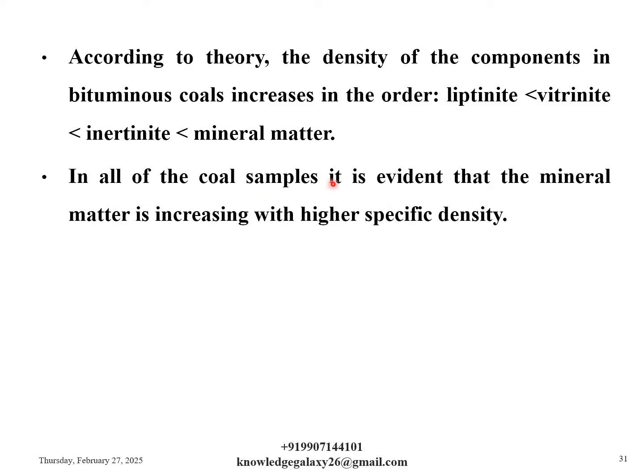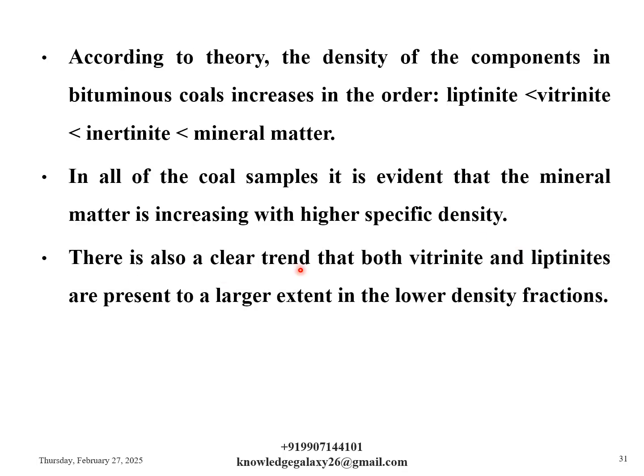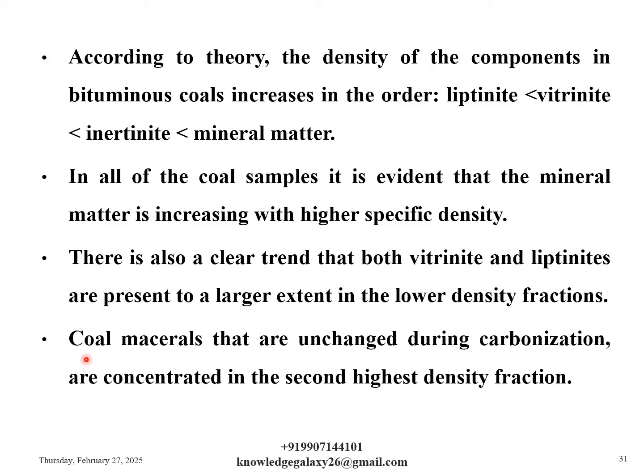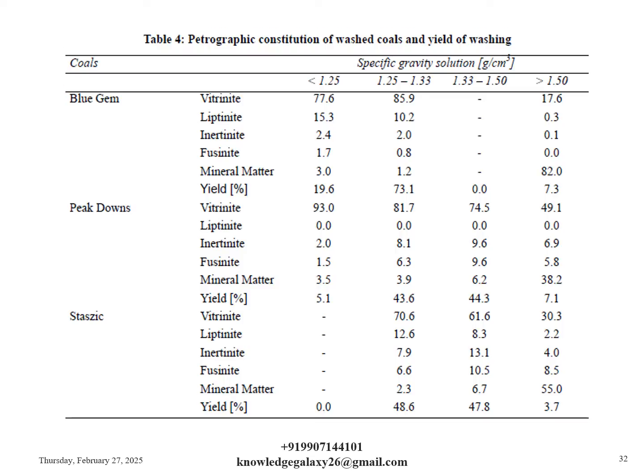In all of the coal samples, it is evident that the mineral matter is increasing with higher specific density. There is also a clear trend that both vitrinite and liptinites are present to a larger extent in the lower density fractions. Coal macerals that are unchanged during carbonization are concentrated in the second highest density fraction. So this is Table 4, which gives the petrographic constitution of washed coals and yield of washing.